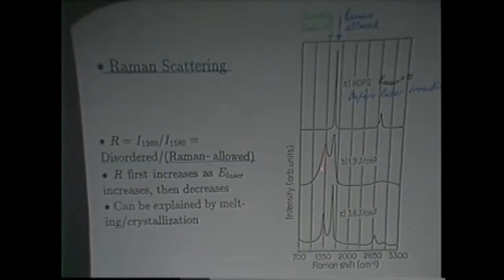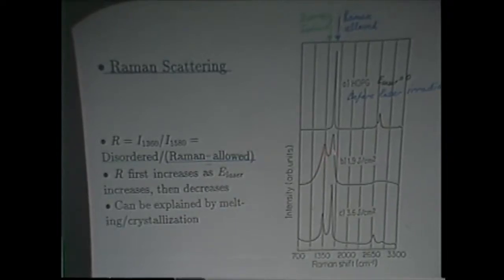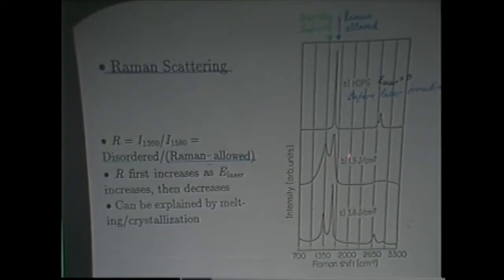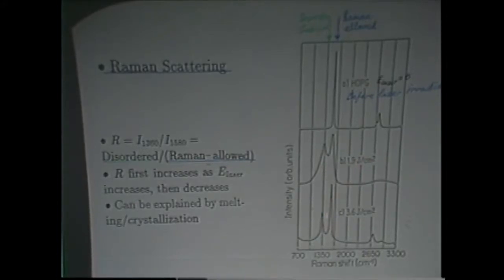And so here's zero before we start the laser irradiation. And after some laser irradiation, in addition to the Raman allowed line, we get a disorder-induced line. And the line widths get kind of broad, indicating we have a rather disordered system. But as the laser energy density increases, instead of getting more disorder, we get less disorder. The lines sharpen up, and we get a spectrum that's closer to that of the graphite.